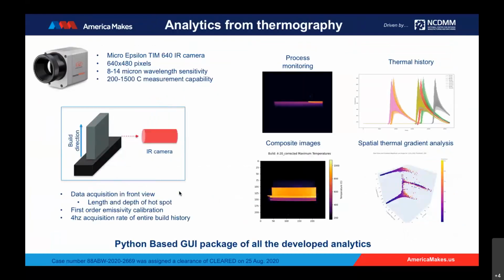So this slide is more looking at the thermography part of it. The Python-based GUI tool was used to analyze the IR thermal data using these laser-based DED approaches. We utilized the IR camera from Micro-Epsilon to capture the thermal history in a front view perspective. That gave us a tremendous opportunity to track the length and the depth of the hotspots in the deposition, observe the thermal history below the melt pool, which is also quite important, and then combining this information, we developed tools for analyzing spatial and temporal variations.